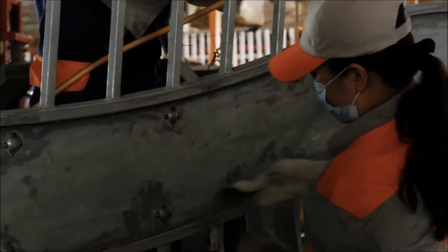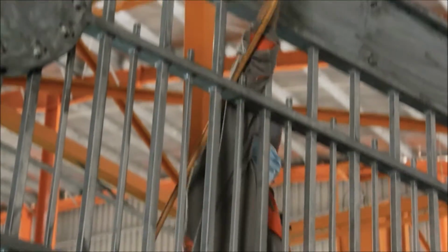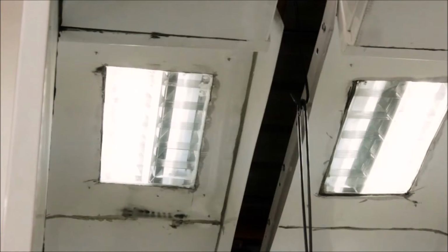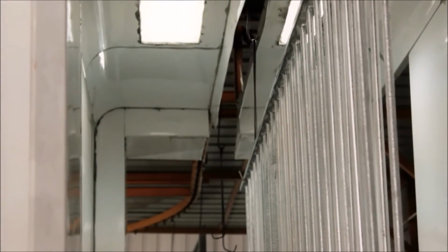So prior to the powder coating of the product, the galvanized product enters into the oven, where the oven is 200 degrees Celsius. The reason we put the galvanized product in the oven prior to powder coating is that during the hot-dip galvanized process, the zinc coating has small little air bubbles in it, which, if not preheated prior to the powder coating, will expand and blow the powder coating off. So we put them in the oven first so that the bubbles expand and release the air out of the zinc coating, so that we don't have any defects on the paint surface after it goes through the oven after powder coating.